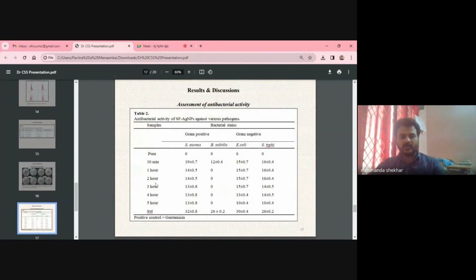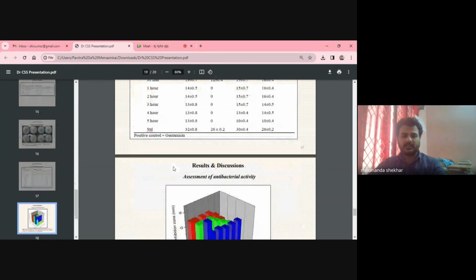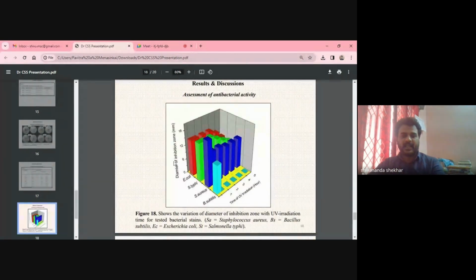So for pure, 1 hour, 2 hour, up to the standard. For the 30-minute irradiation, we get a larger zone of inhibition, because in 30-minute irradiation small sized nanoparticles are formed. That's why it is able to kill more than the large sized nanoparticles. So this is a schematic table for the antibacterial assessment, and this is a 3D graph for the antibacterial assessment.